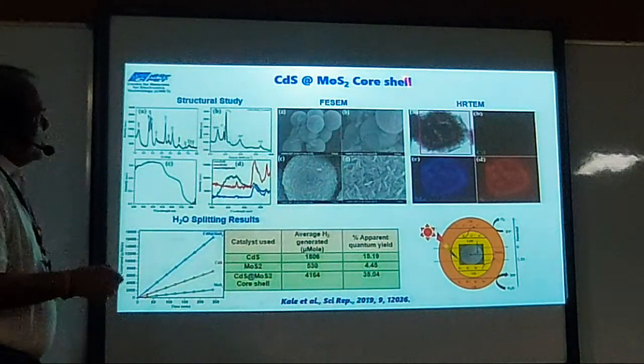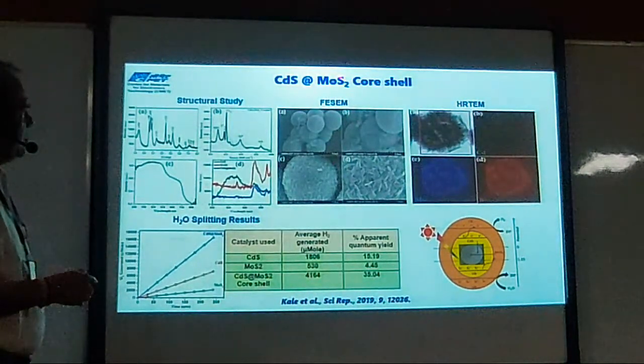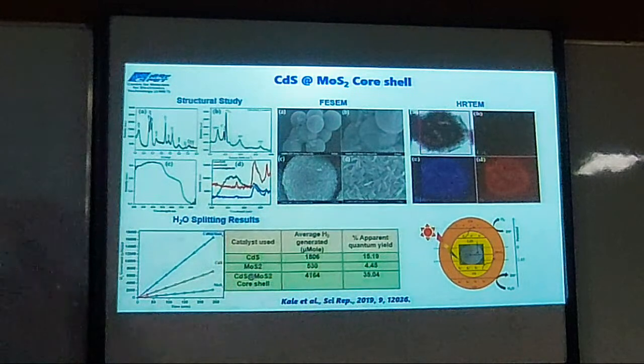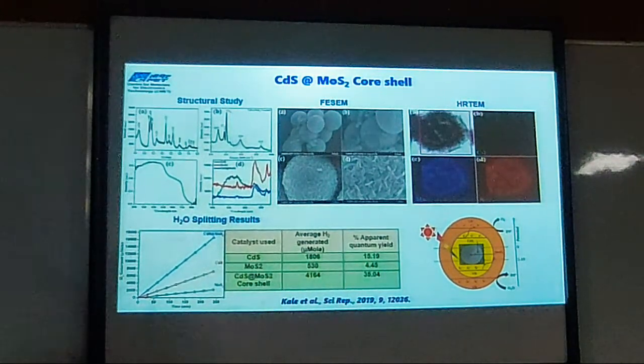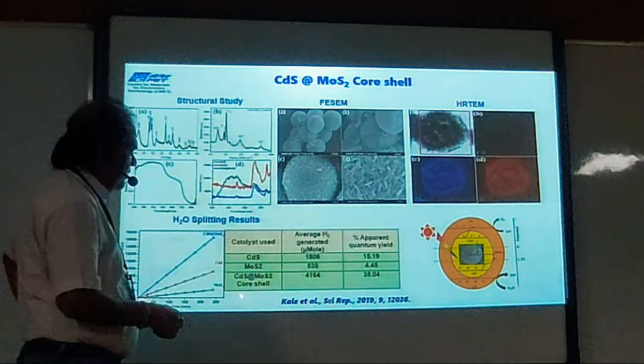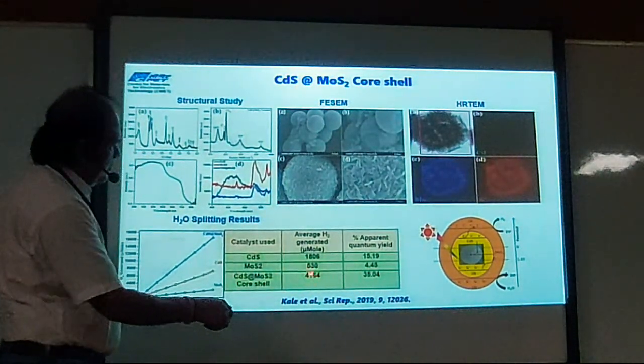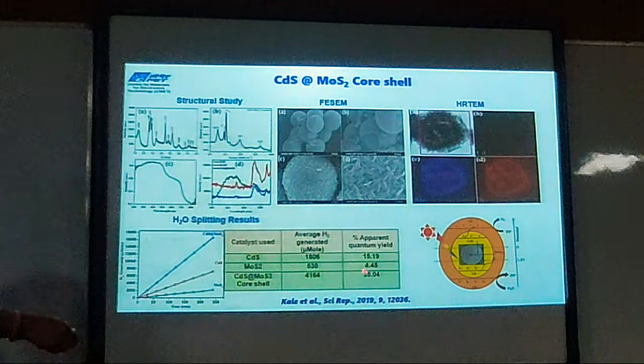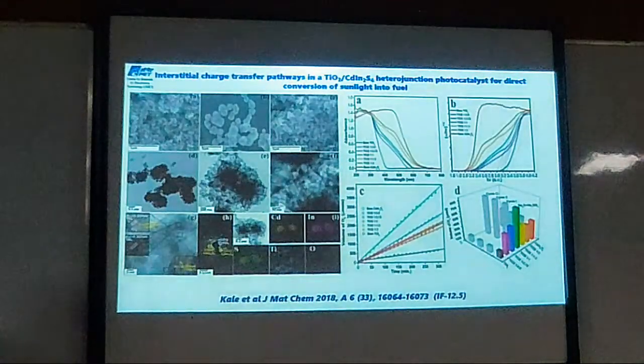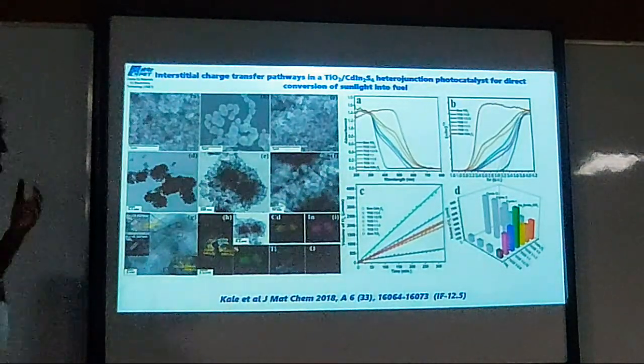So we got a very good publication on it, in JMCA. We explained how these structures are important for hydrogen production. Then we did a core shell. We thought about whether we can have, on the MoS2, a small thin layer of CdS, and we found that it also works very well when we have core shell. We get almost 35% quantum yield.